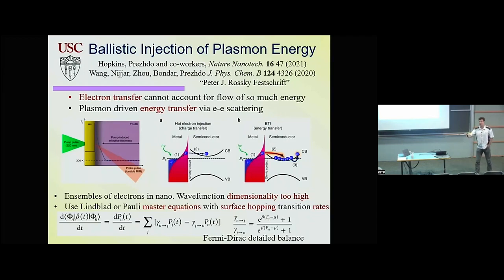You don't have charge transfer, but what you have is scattering, or an Auger-like process, of excited electrons in the metal with the doped electrons in the semiconductor. And this scattering creates transport. And then if you have another metal on the other side, they scatter with the second. They go into the second metal, scattering with the electrons in the second metal. And then the electrons in the other metal relax to the ground state, and you cannot go back because you're already in the band gap in terms of energy. So Auger processes are very important for transport in these systems, not just charge transfer.